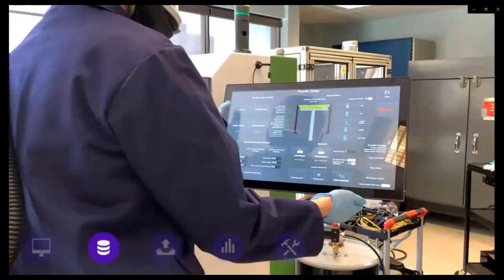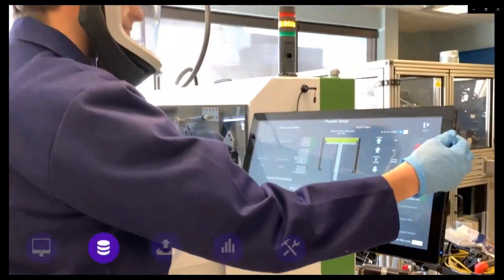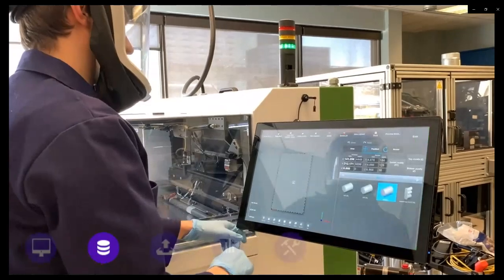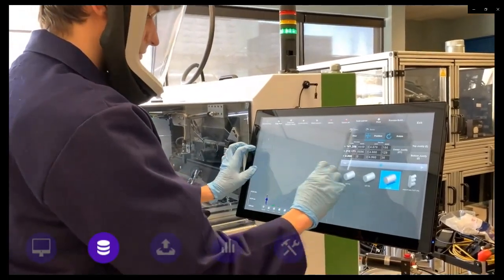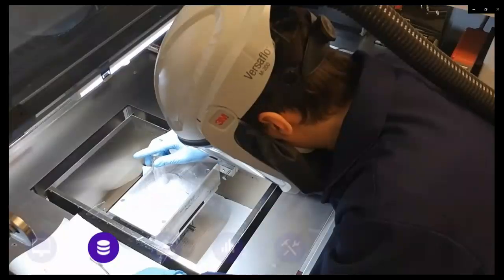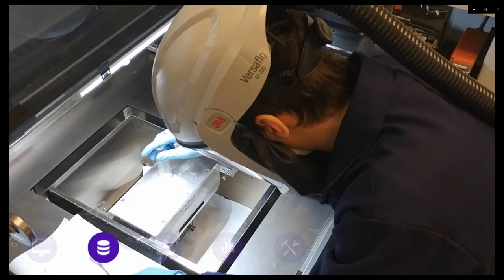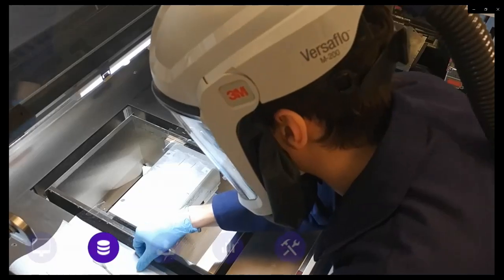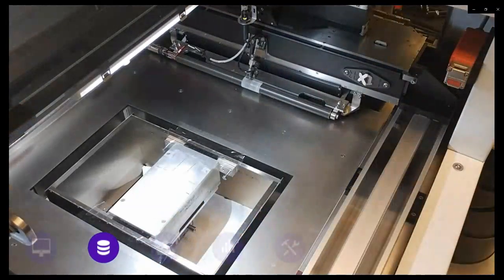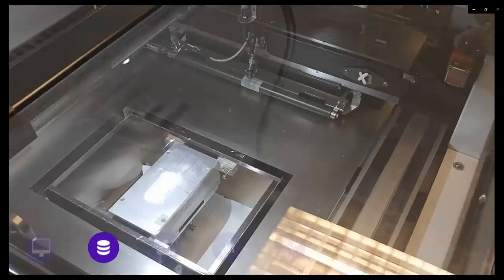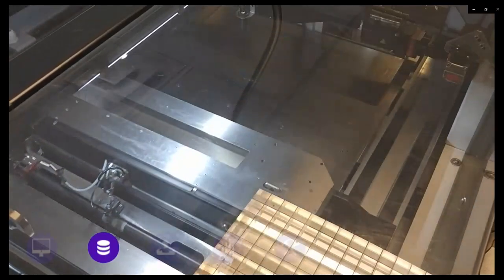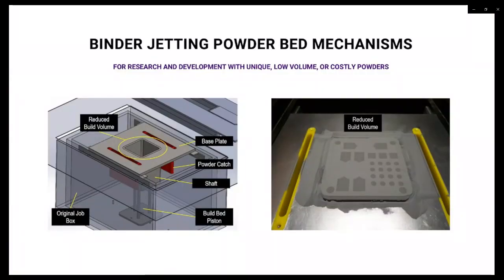Digital file manipulation, part orientation, and process parameter setup. Each material and design will have its own optimized process parameter library. The machine operator, depending on the material type, can load powders into a hopper system to dispense powders onto the build platform, or the operator can manually fill a feeding bed mechanism with raw materials as shown here. Here we see an example of a machine modification to allow work with smaller quantities of powders. The build platform can be large, almost 0.5 meters, or small, a few centimeters.